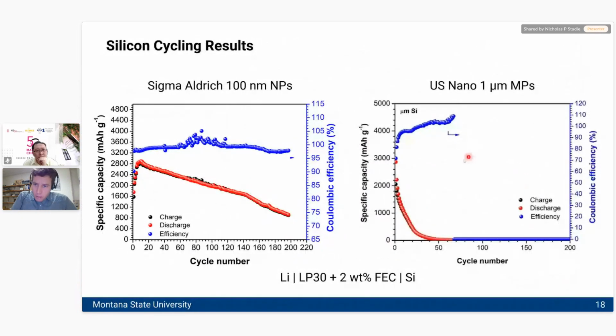Here is just some raw data. These were collected pretty early on in our investigations of lithiation of silicon. We basically just bought silicon off the shelf in the form of 100 nanometer nanoparticles from Sigma Aldrich, and we made our electrodes in the same way as we'd make a graphite-based electrode. What you're seeing on this plot is the discharge capacity of that electrode in a half cell configuration as a function of cycle, in red. And in blue, we're seeing the Coulombic efficiency, which is really just the discharge capacity divided by the charge capacity. This fraction should be equal to 1 if things are behaving well in the cell.